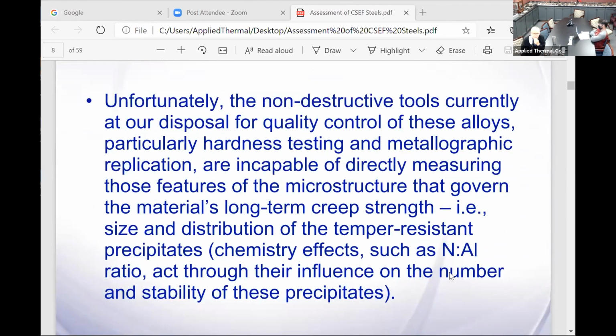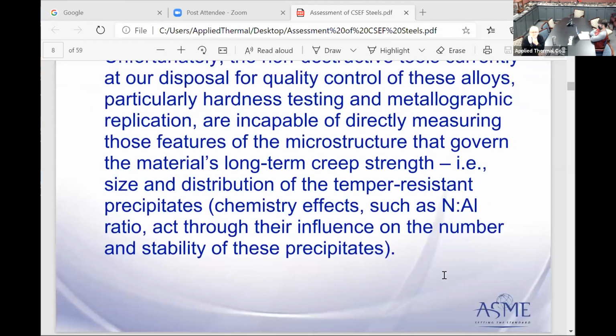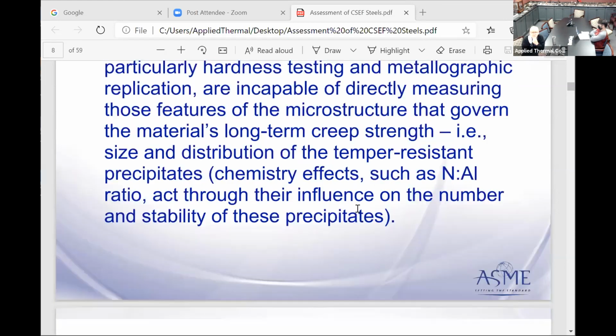Basically, the non-destructive tools that we currently use when we go out in the field, in this case particularly hardness testing and replication, are incapable of directly measuring these features of the microstructure that govern the material's long-term creep strength. That is, you can have properties that are still good, except your creep strength will be degraded significantly. And Dr. Joe mentioned a few things about composition, obviously chemistry effects: nitrogen, aluminum, all these things affect the influence and stability of the precipitates in the material.